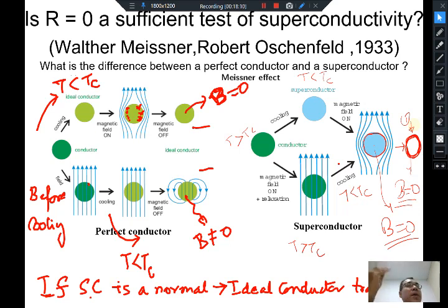So this shows that the superconducting transition is a true thermodynamic transition in the system, where the electronic state of the system is doing something different. It is going into a completely different phase because it no longer behaves like an ordinary conductor or an ideal conductor, but completely differently. Irrespective of the path taken, it is expelling all magnetic flux from within its interior. And this is the importance of the Meissner phase. This is the true test of superconductivity. If you want to test if a material is superconducting, do the Meissner effect.